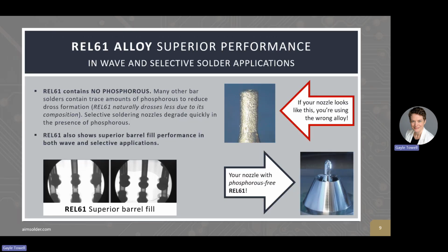REL61 is really great for wave and selective soldering applications. Oftentimes, people ask about phosphorus content. Some alloys have phosphorus added in for wave soldering to reduce dross, but REL61 does not. We do not add phosphorus to our REL61. REL61 actually naturally drosses less due to its composition. Phosphorus in selective soldering applications can degrade nozzles. Since REL61 does not contain phosphorus, this is not an issue. REL61 also shows superior barrel fill performance in both wave and selective soldering applications.